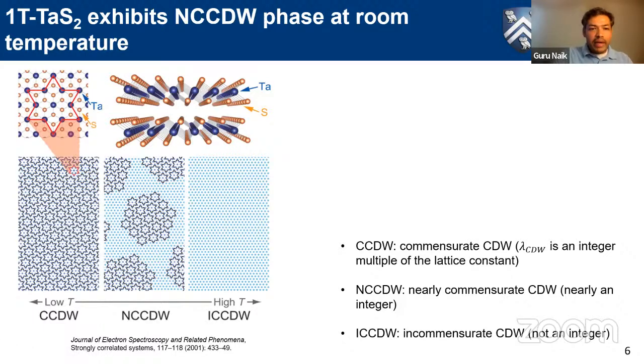It has both a Mott gap and a charge gap. And the Mott gap vanishes somewhere about 180 Kelvin. And then beyond that, even at room temperature, there is still a charge gap. And the charge gap vanishes somewhere about 80 degrees centigrade. So at room temperature, there is a strong charge gap that exists in this material.